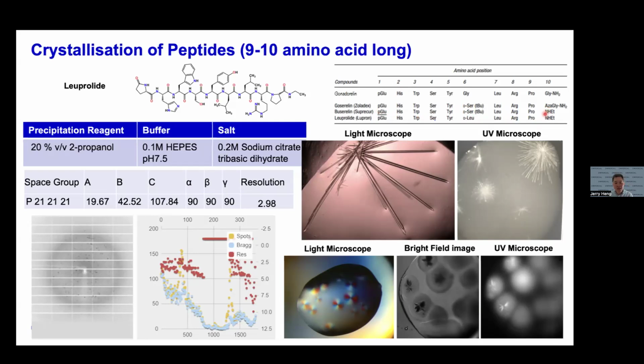And screening conditions is quite tricky. We've spent over 2 years, and we were only able to crystallize one of these 4 peptides in a specific condition as reported here, confirming that this crystal is indeed a peptide crystal by use of light microscopy or bright field UV microscopy. So we're quite happy there, although we've not quite been able to solve this crystal structure yet.